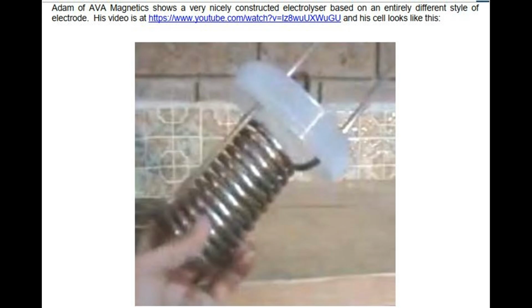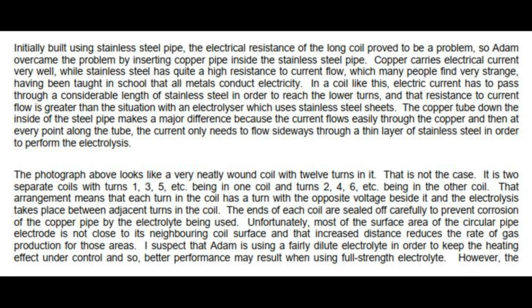Copper carries electrical current very well, while stainless steel has quite a high resistance to current flow, which many people find very strange, having been taught in school that all metals conduct electricity. In a coil like this, electric current has to pass through a considerable length of stainless steel in order to reach the lower turns, and that resistance to current flow is greater than the situation with an electrolyser which uses stainless steel sheets. The copper tube down the inside of the steel pipe makes a major difference because the current flows easily through the copper, and then at every point along the tube, the current only needs to flow sideways through a thin layer of stainless steel in order to perform the electrolysis.